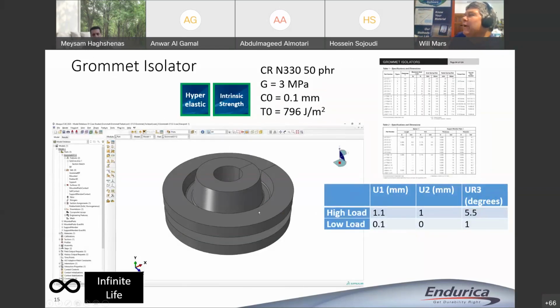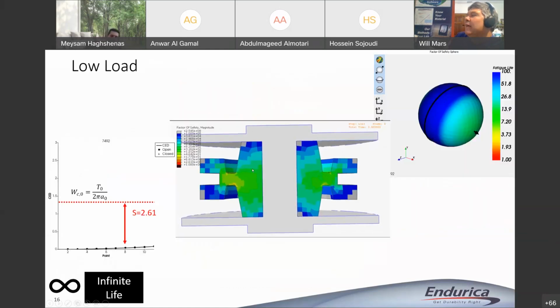So here's my grommet example. In this case, we're going to model 2 loads. One is going to be at a low load, and one's going to be at a high load. We're just going to measure the stiffness of the rubber, the precursor size of the rubber, the fatigue limit of the rubber. We feed that into these calculations, and here's what you get.